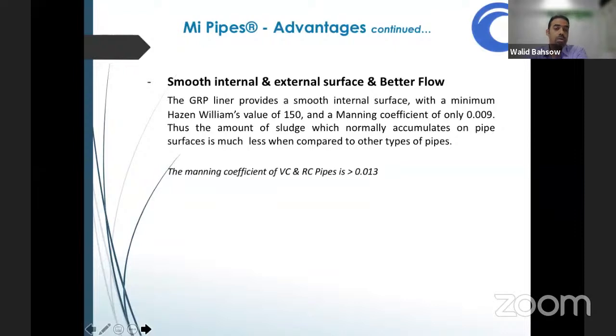So we have the smooth internal and external surface and the better flow. The GRP liner provides a very smooth internal surface, which has a minimum Hazen-Williams value of 150 and a Manning coefficient of 0.009. Thus, the amount of sludge which would normally accumulate on pipe surfaces is much less when compared to other types of pipes. The Manning coefficient of the vitrified clay pipes and the RC pipes, the reinforced concrete pipes, is greater than 0.013, and this will deteriorate with time.